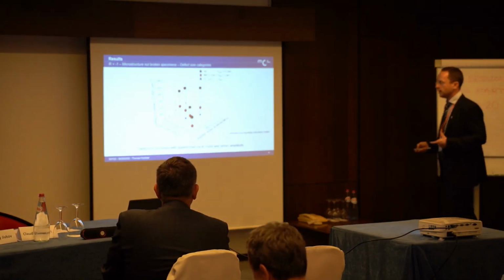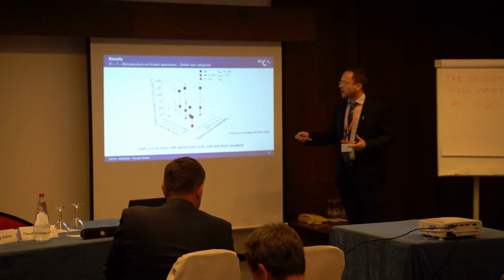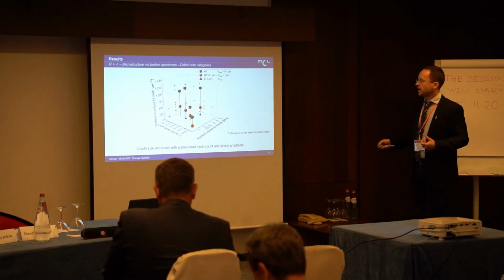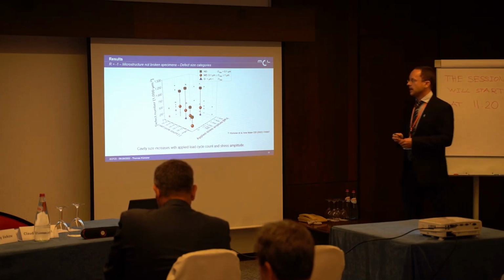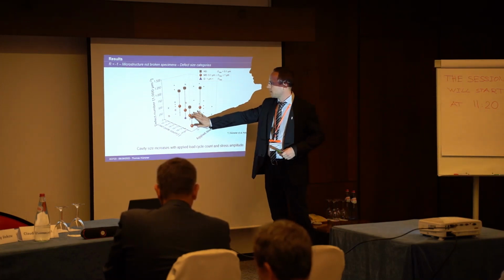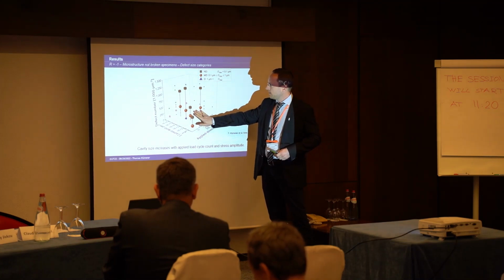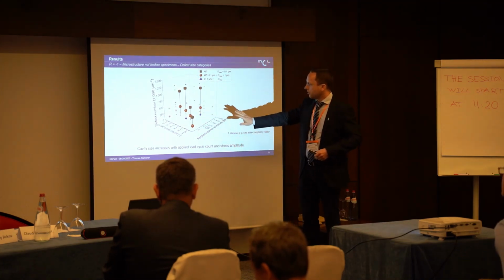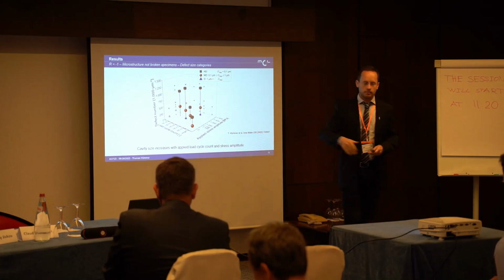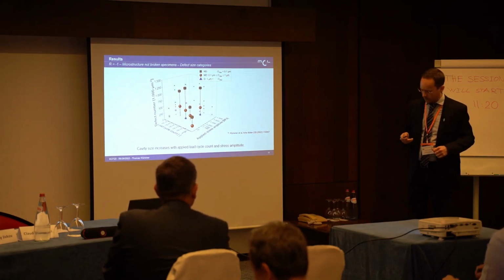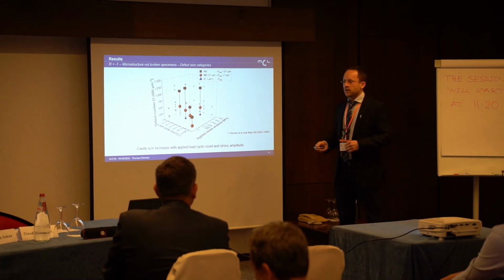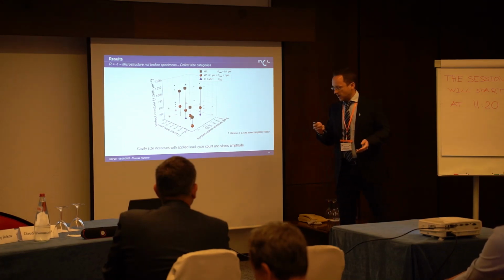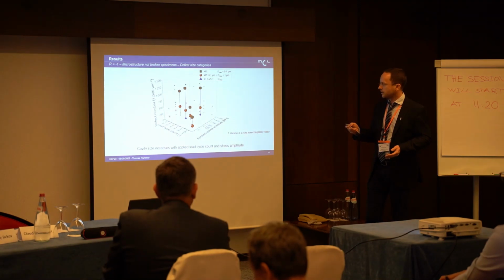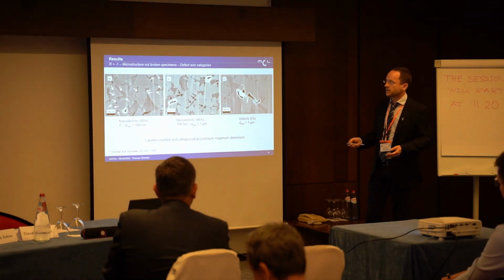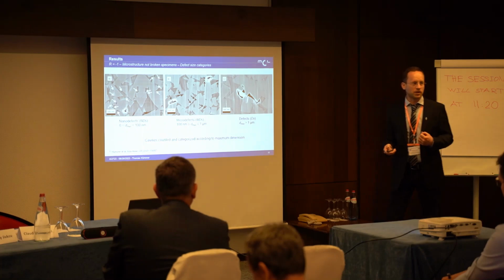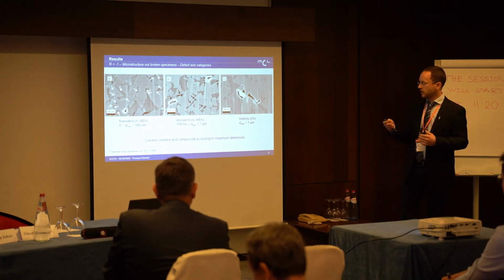So when we categorize them, count them, and plot them here, the defect number per unit area, load cycle count, and applied stress amplitude, we see the nano-defects compared to the virgin material. You see here, this is the nano-defect symbol. They rise with both quantities and reach a plateau. Because you saw maybe in the previous image, every site where stress concentration is rather high forms such a nano-defect at some point. So there's a saturation in this number.